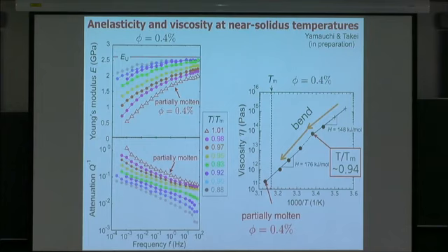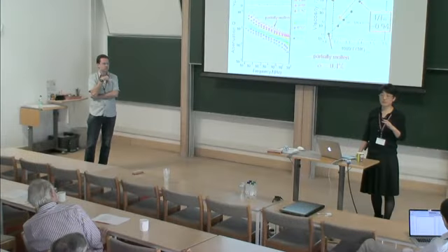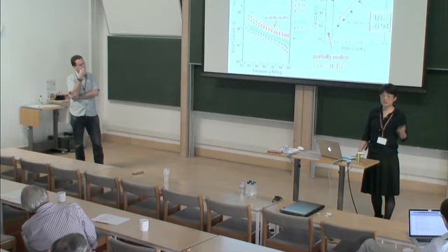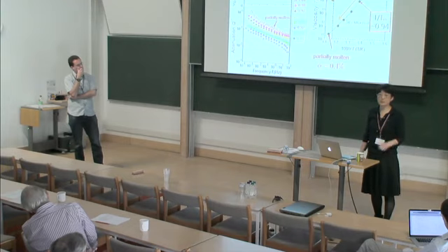The ratio of P wave velocity to shear wave velocity is often used as evidence for melt. Can you speculate how that might be? This anelasticity is grain boundary sliding, we consider, so it affects shear modulus but not bulk modulus.